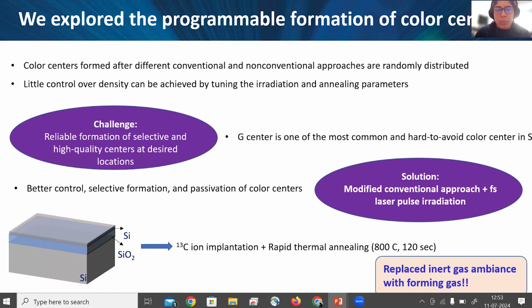So it's important to study and make all these qubits on silicon on insulator devices so that we can directly switch from one single qubit level to a full-scale quantum network. So what we essentially do is first start with this wafer, then do carbon ion implantation to introduce carbon in the wafer, and then do a thermal annealing process, which people have been doing.